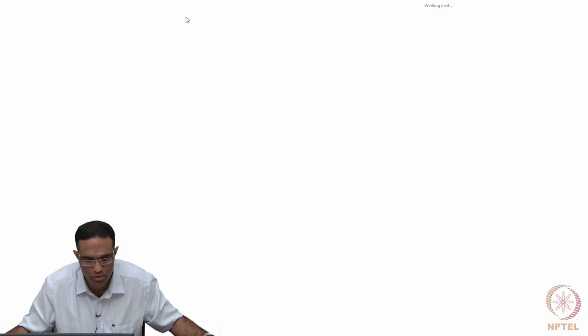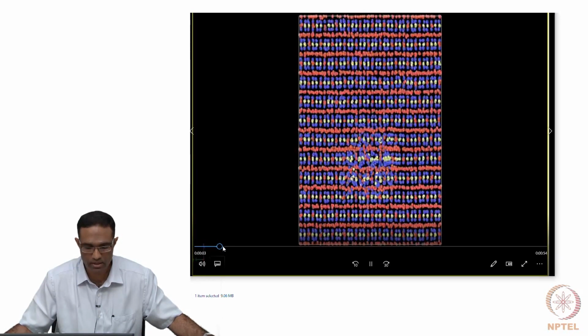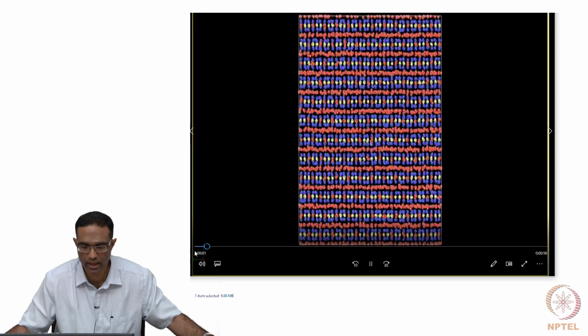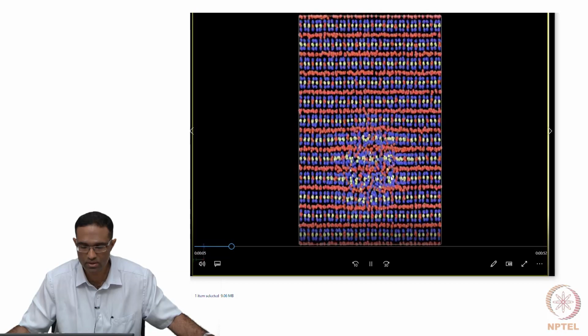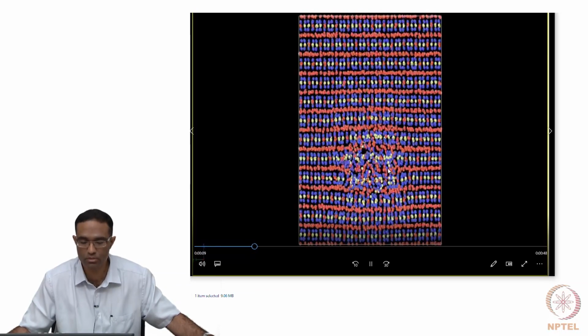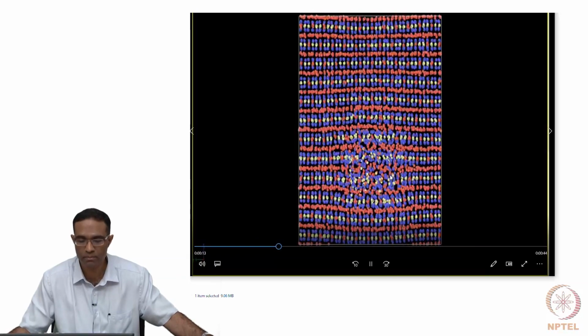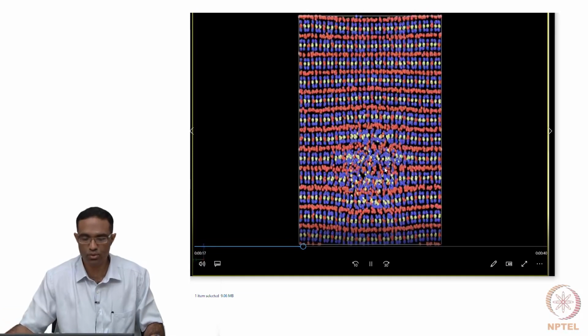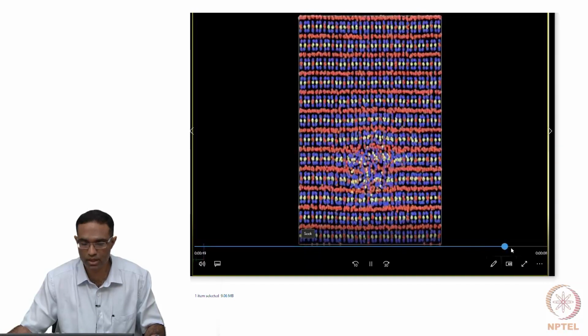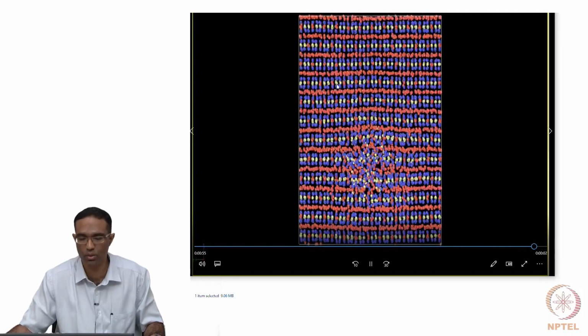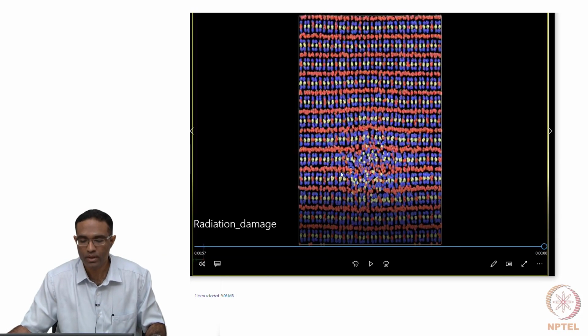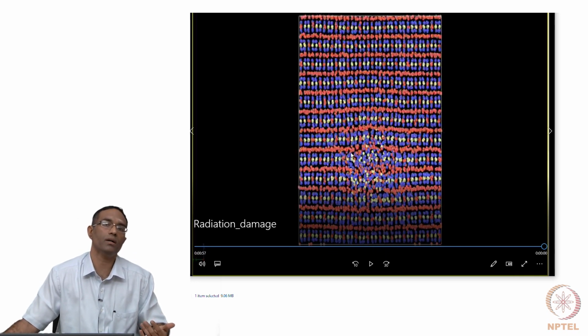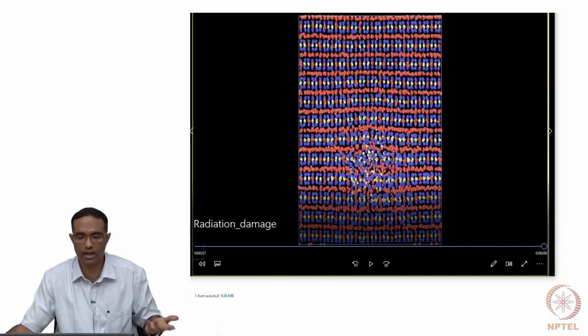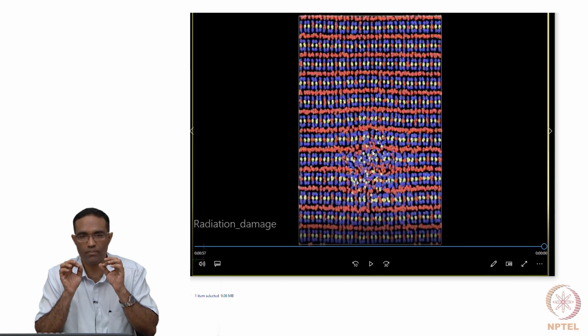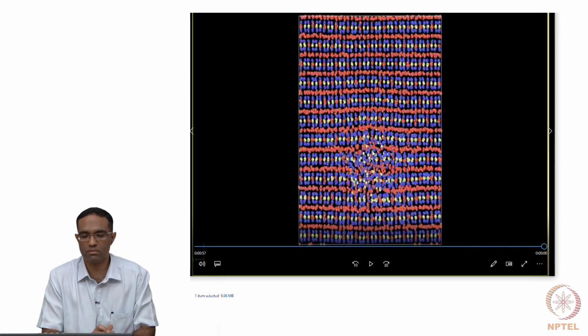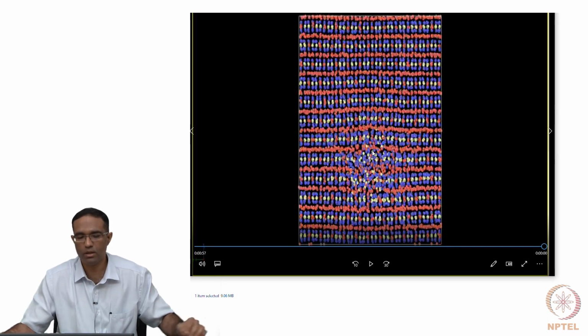I will show you some videos. This is an example of lithium metatitanate, and you can see one particular atom moving all of a sudden and creating a small cascade region here. This is a molecular dynamic simulation of this cascade event in lithium metatitanate. If you wait long enough, after some time you create a small region which consists of point defects, whereas the remaining region surrounding it is still perfect crystal. What we are interested in is how these point defects evolve with time, and what is there at the end of the cascade. Cascade means the process by which the atom bombards this material to create point defects.